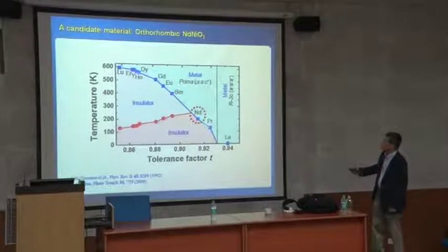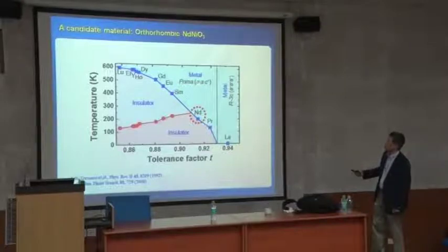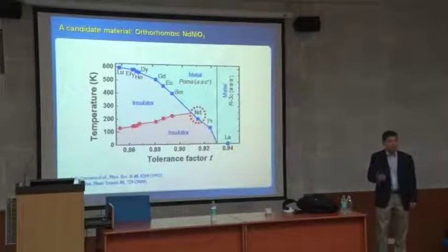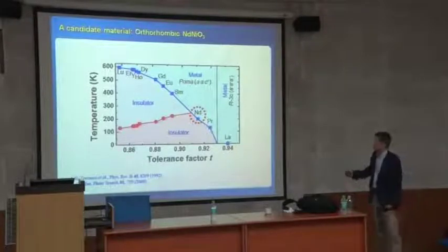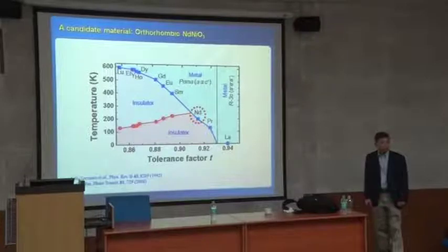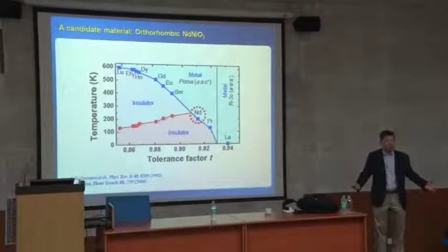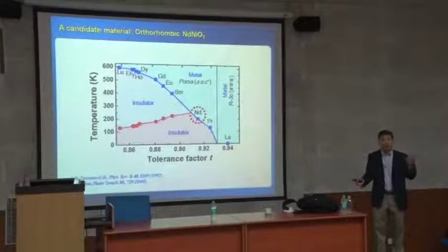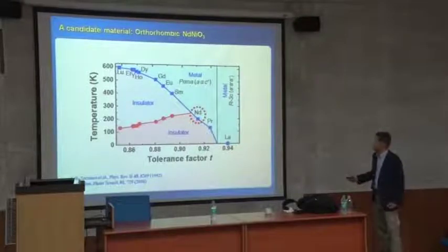rare earth nickelate, okay, this phase diagram, rare earth nickelate, and this crystal structure of all those things, the same kind of structure, orthorhombic structure, Pnma, the space group, but minus, minus, plus, and that's a tilting pattern, it's minus, minus, plus pattern, and then you have different elements here. But this one is all insulators. Okay, so you have an insulator, then it's already disqualified, because you want to be metal. You start with the metal. So which one is a metal? You have only two of them is a metal here with a possibility.